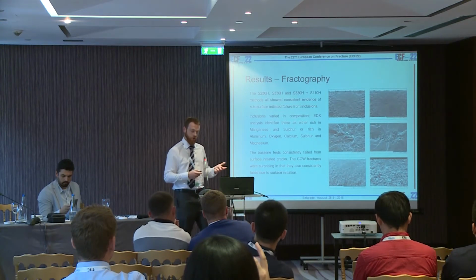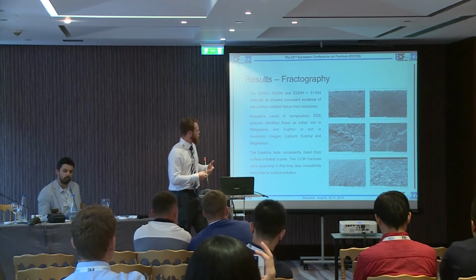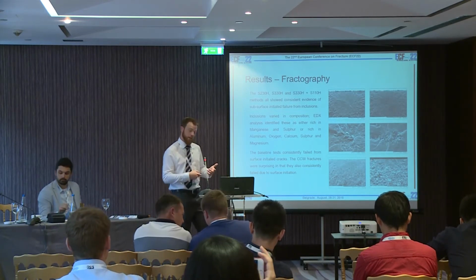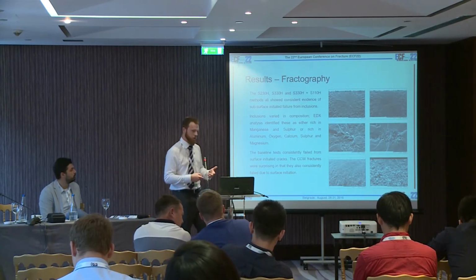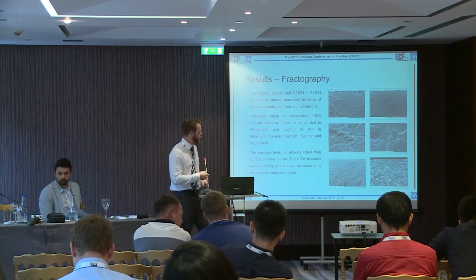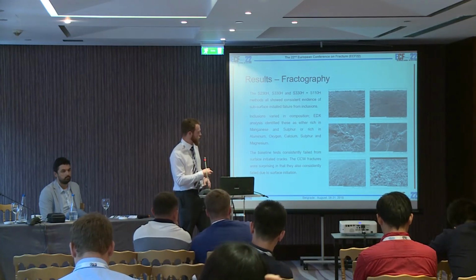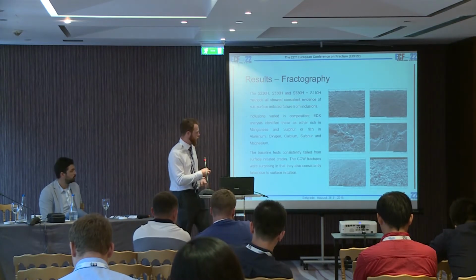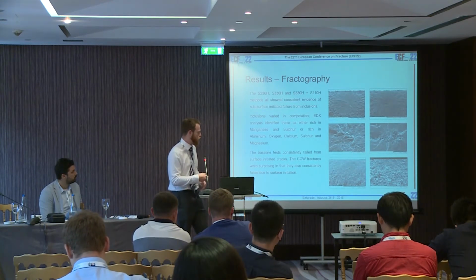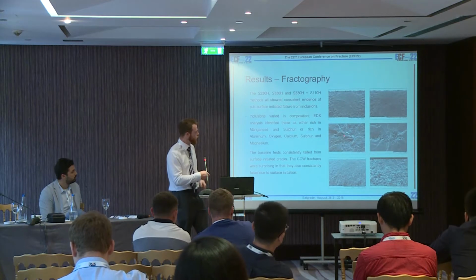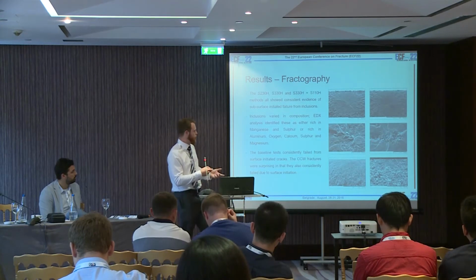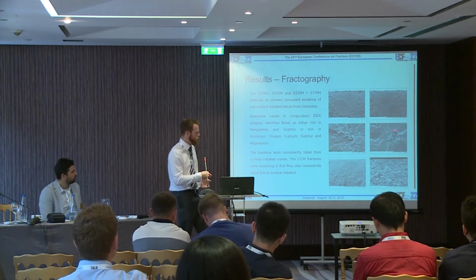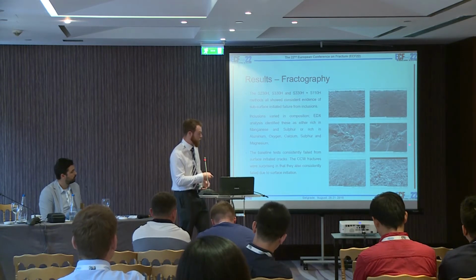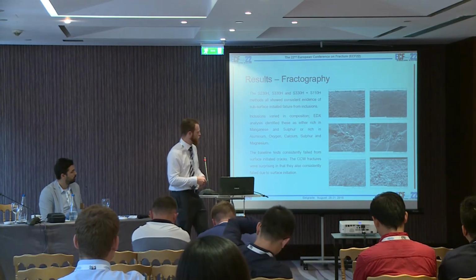So some fracture faces from these results. The S220 and the S230 and S330 gave us results as we would expect, as did the duplex process, and we consistently saw subsurface initiated fractures from inclusions in the steel. Two examples here, I think this is the 230 and this is the 330, but they were all broadly the same. I'm just trying to show you two good examples. For example, from a manganese sulfide inclusion, or I think this is aluminium oxide cluster. There's some manganese sulfide included in there as well, and these tend to form in clusters.